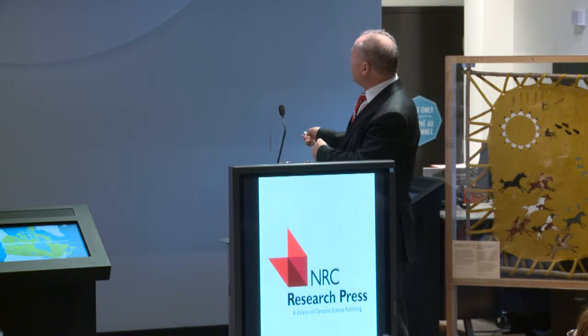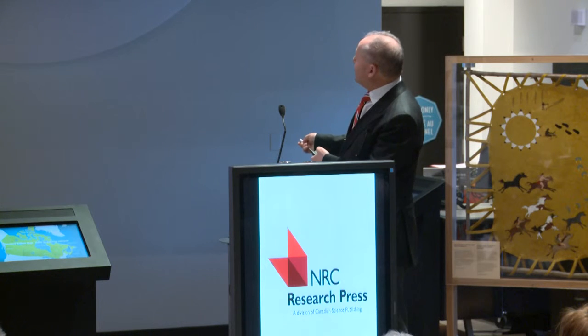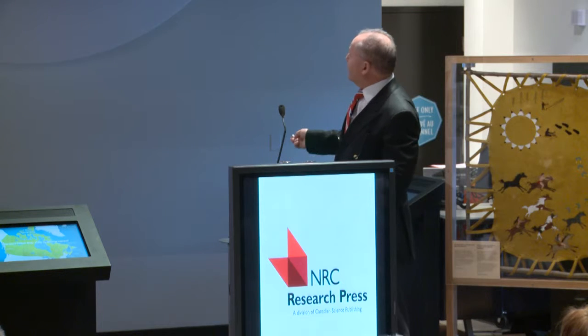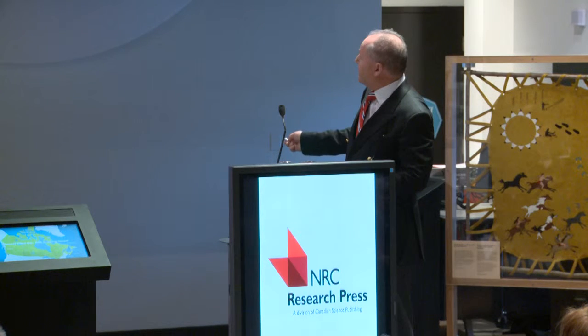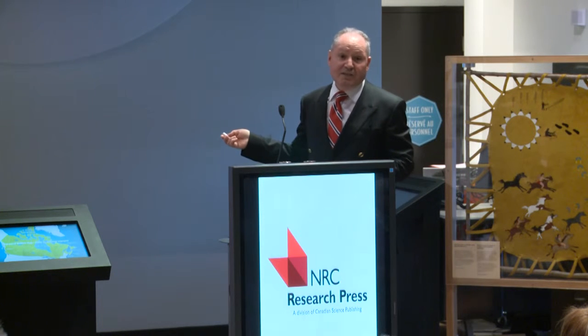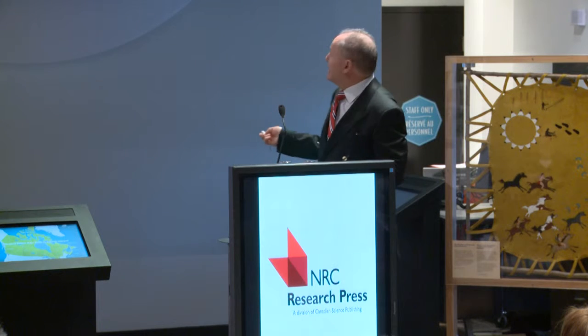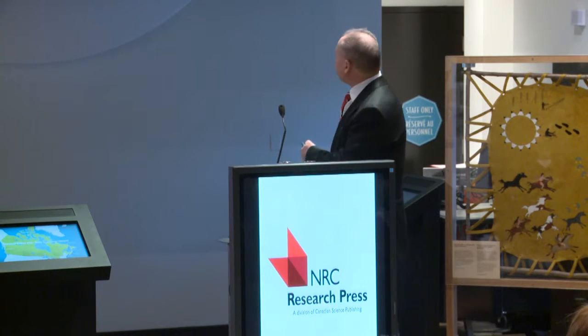This is also another kind of deterioration here. And unfortunately, sometimes, here I'm showing you in parking garages, this could even bring failure, as you can see here. As you know, the floor of the parking garage was at this level, and due to the corrosion, this parking garage collapsed, and unfortunately, two, I think, or three people died. This was in 2008 in Montreal, in Saint-Laurent, where this case happened. And as you'll see later, the solution that we proposed, and also the new innovative parking garages that we built during the last few years.